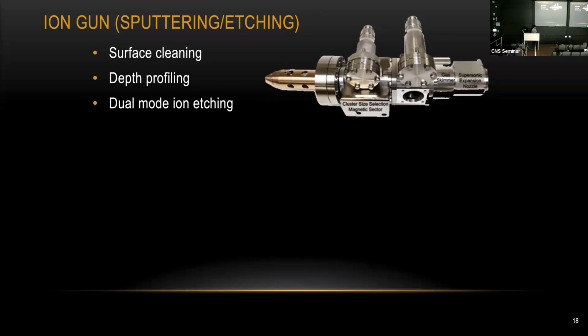So what can the ion gun be used for? It can be used for some surface cleaning. As I mentioned earlier, most of the samples coming here definitely have some sort of contamination on top, and the most common contamination you're going to see is hydrocarbon contamination. So we might need to do some surface cleaning to remove the top layer and get a measurement from the clean surface. We can also do some depth profiling, which means we do scanning and etching multiple times and try to see how your material has changed in the Z direction.